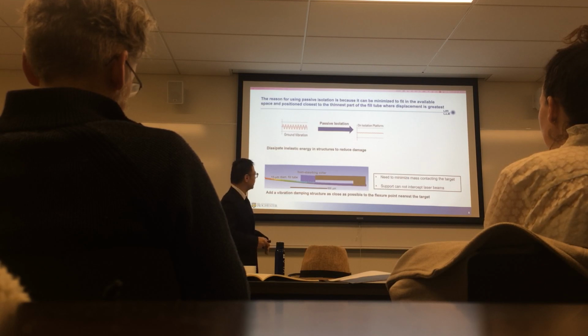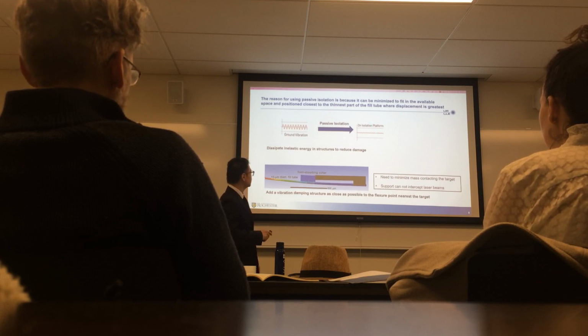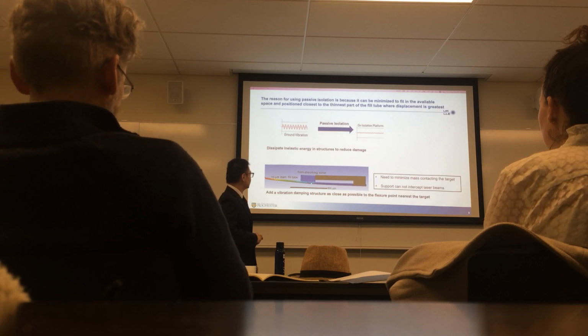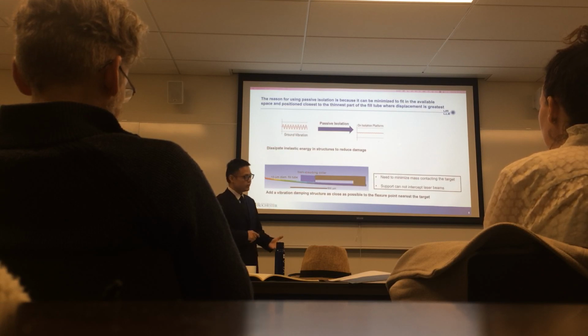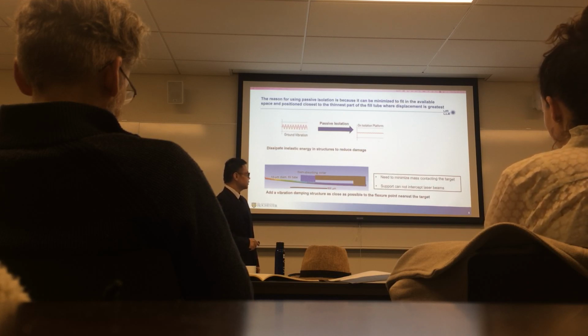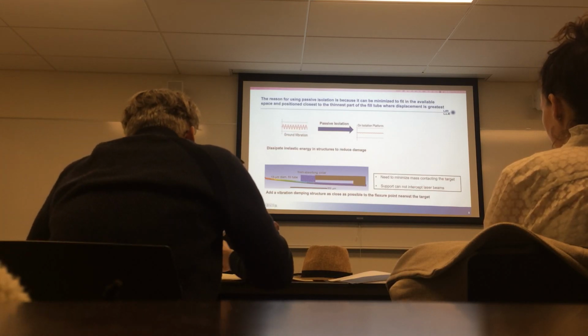So we want to develop a foam structure around the fill tube to act as a passive isolation. And this foam structure will not only dissipate energies, but also have a density as low as possible and be as small as possible. Meanwhile, this foam structure should have a minimum mass contact with the capsule and should not block the laser beams when they do the laser fusion test.